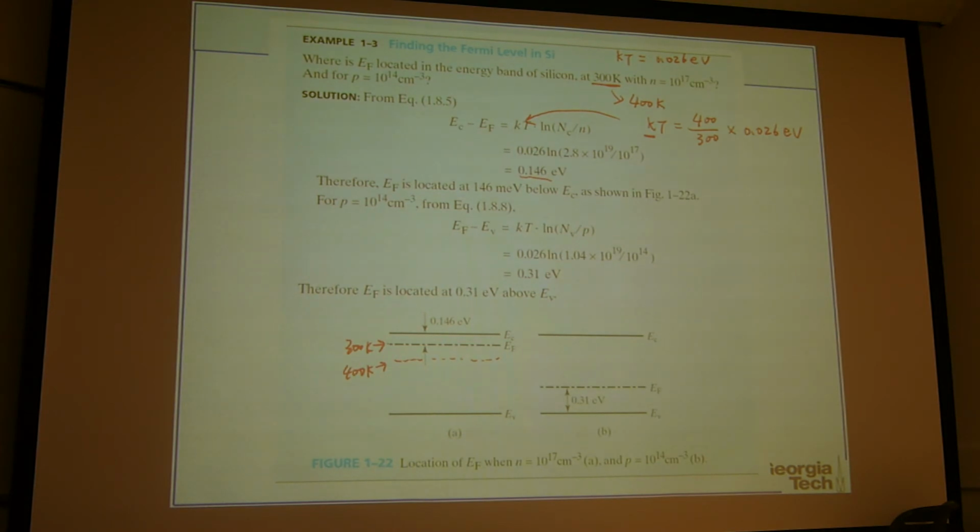Exactly. So as you increase the temperature, you are going to get more thermally activated electron hole. We talked about earlier, right? There are two ways to introduce the electron hole. One is by this intrinsic thermal vibration. You break the bond, then you get the electron hole pair. But at room temperature, the probability is very low. So the electron is dominated by the external dopant, right? You have the dopant. So that's why you have the Fermi level close to the EC.